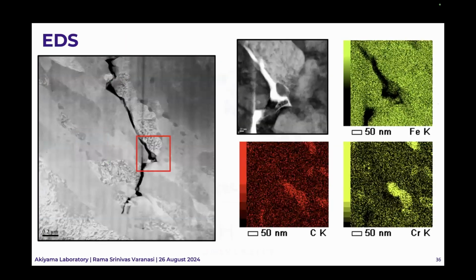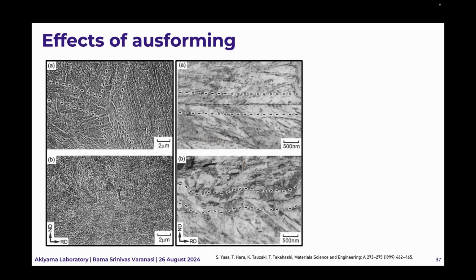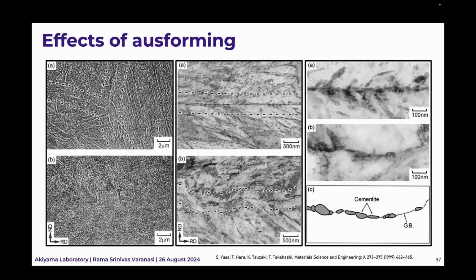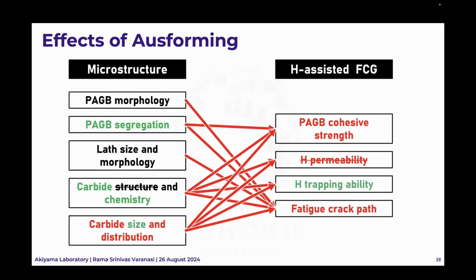And when we look at it, we clearly see there's a carbide, and this carbide is having a decohesion at the boundary. However, this is a smoking gun for us, that when we have these carbides at the prior austenite grain boundaries, these also would enhance the decohesion in the presence of hydrogen. And this was also previously reported that because of Ausforming, the carbide density at these prior austenite grain boundaries reduces, and that is also what we observe here.